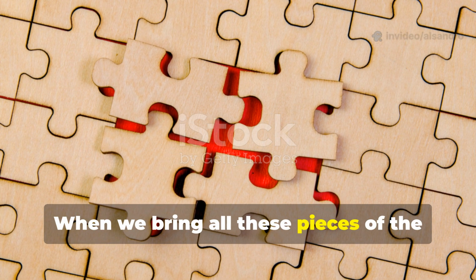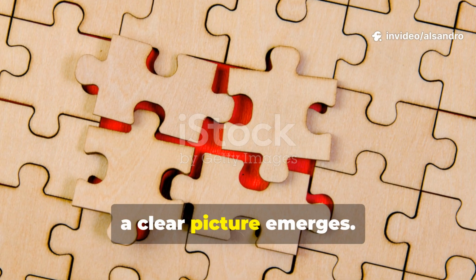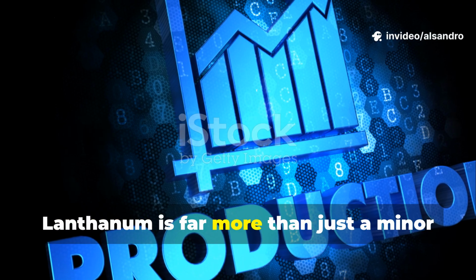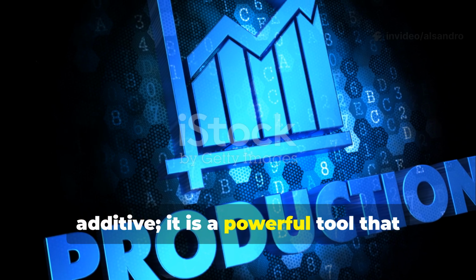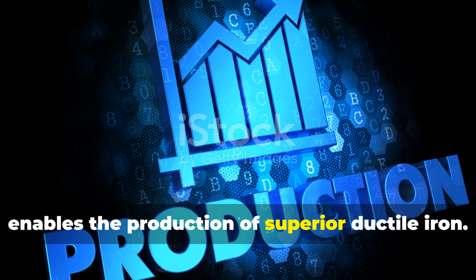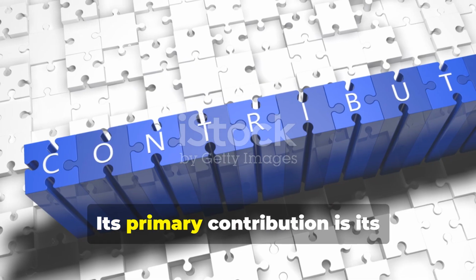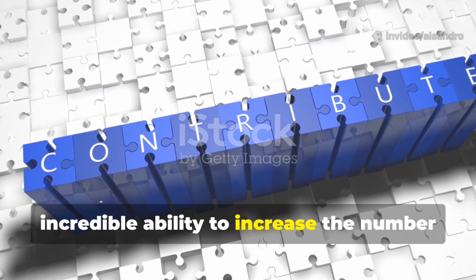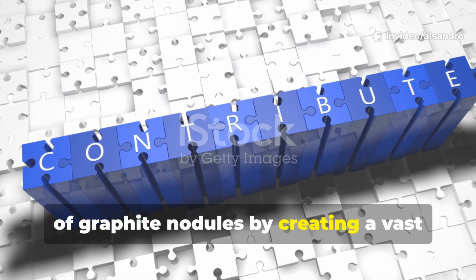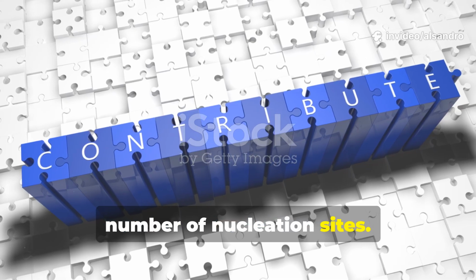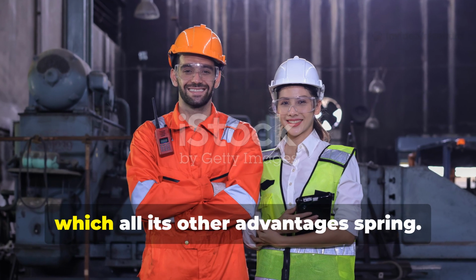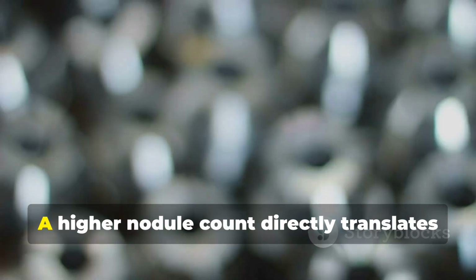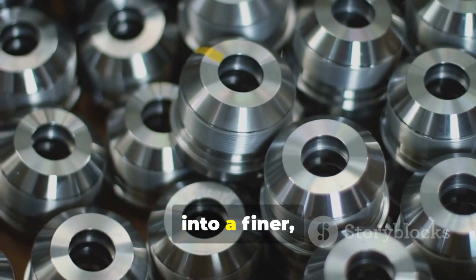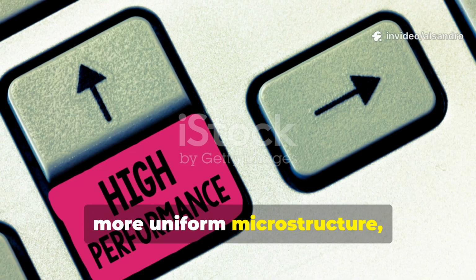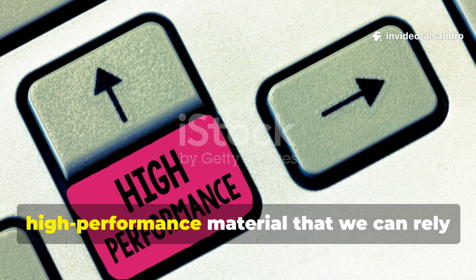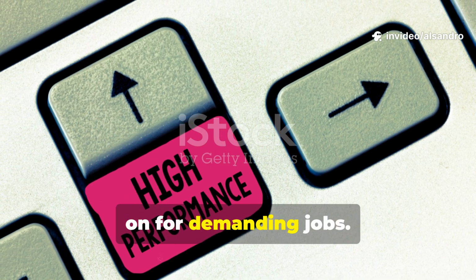When we bring all these pieces of the puzzle together, a clear picture emerges. Lanthanum is far more than just a minor additive. It is a powerful tool that enables the production of superior ductile iron. Its primary contribution is its incredible ability to increase the number of graphite nodules by creating a vast number of nucleation sites. This is the foundational benefit from which all its other advantages spring. A higher nodule count directly translates into a finer, more uniform microstructure, which is the very definition of a high-performance material that we can rely on for demanding jobs.